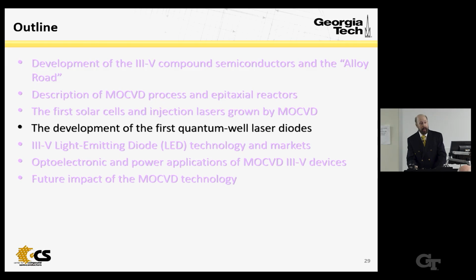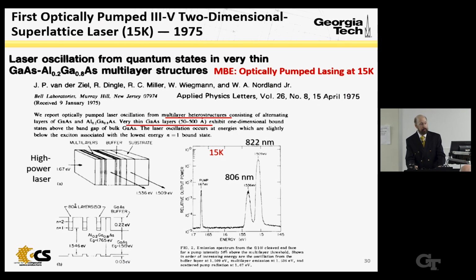So people who had access to MBE systems were excited to try to develop a new series of lasers that used quantum size effects. And this is the result, the first quantum size effect laser, optically pumped only, no diode, at low temperature only, at 15 Kelvin, by van der Ziel and his colleagues at Bell Labs Murray Hill. And they reported aluminum gallium arsenide based double heterostructures.